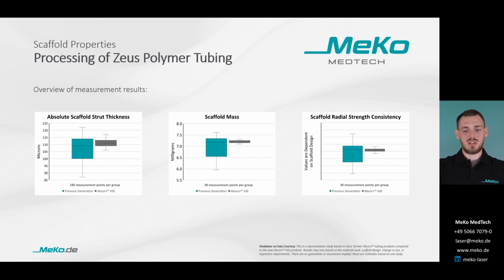The scaffolds then have been tested in the MeKo MedLab for strut thickness, which is shown on the left, scaffold mass in the middle, and radial strength consistency on the right. The strut thickness is directly linked to the wall thickness of the tubing, while the scaffold mass is a combination of wall thickness and strut width consistency. The latter is determined by the laser cutting.